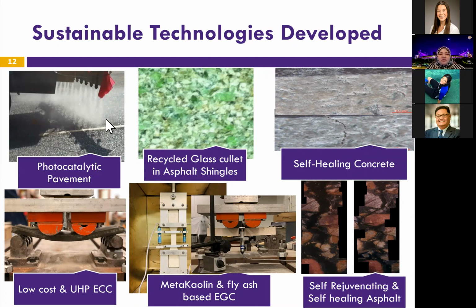We had the first field studies in the US that tested both asphalt and concrete photocatalytic pavements. This picture is from a product that we developed where we recycled beer glass, like glass cullets, in asphalt shingles. And we designed a new generation of shingles that can be a solution to the urban heat effect. And we actually applied for a patent for this technology.